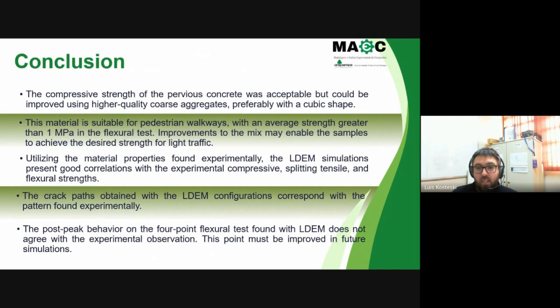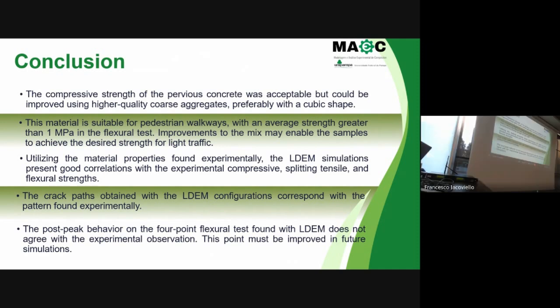Utilizing the material properties that we found experimentally, we have good results with the LDEM simulations, principally for the strengths that we find and the failure configurations. The crack patterns are very similar to the experimental ones. We need now to work to capture well the post-peak behavior of the 4-point flexural test, which we have problems with for now. Well, this is the work that we are doing for now.